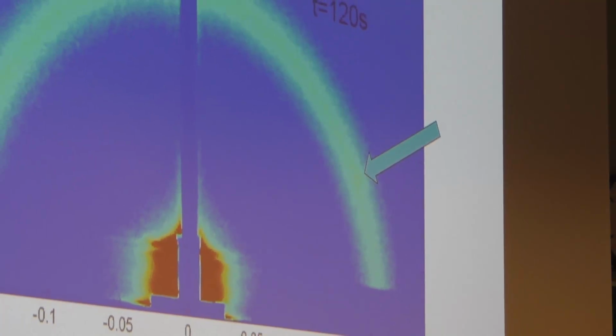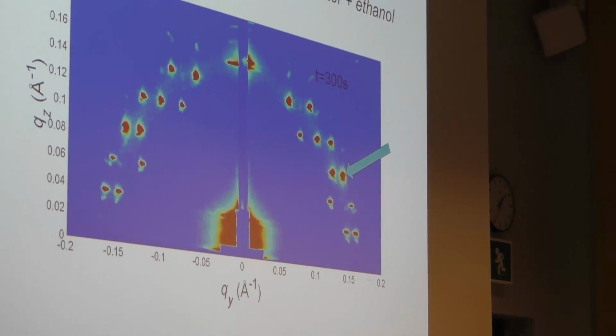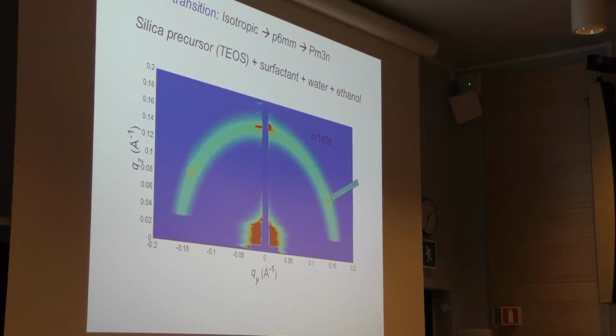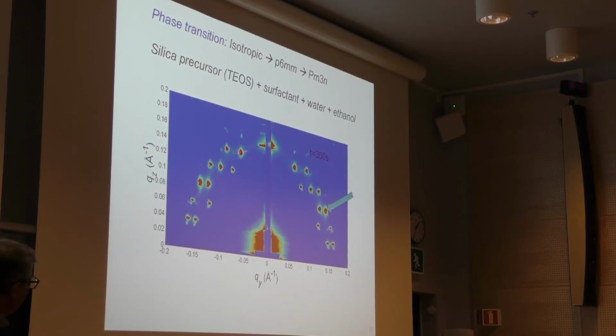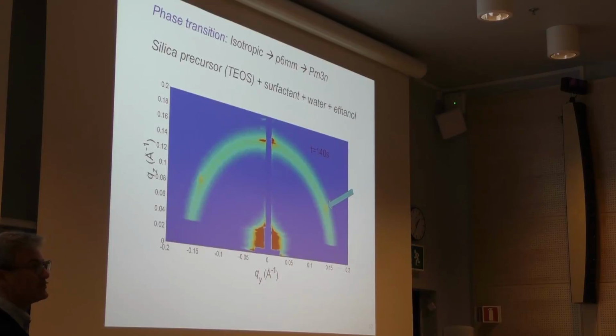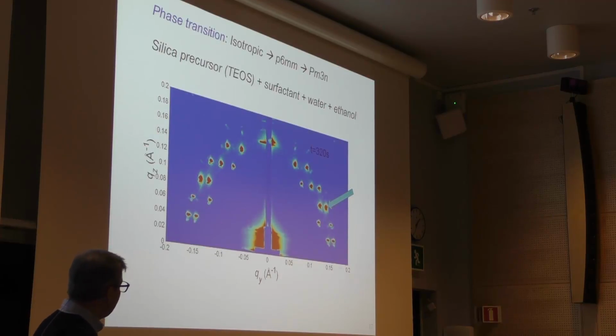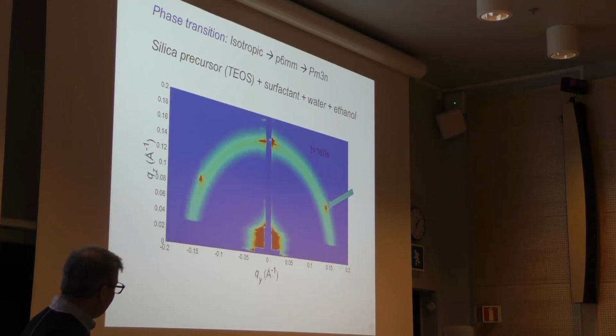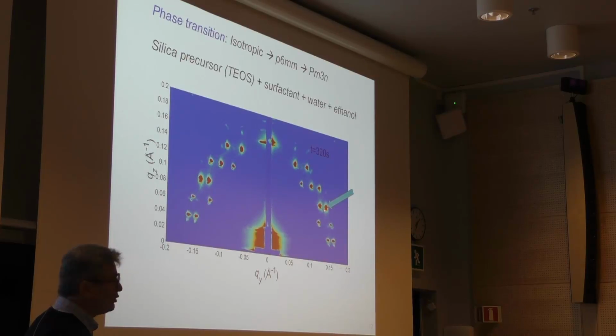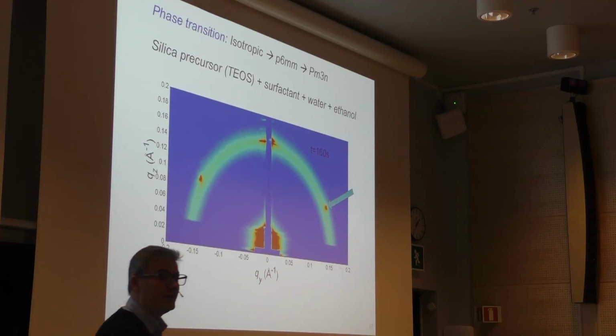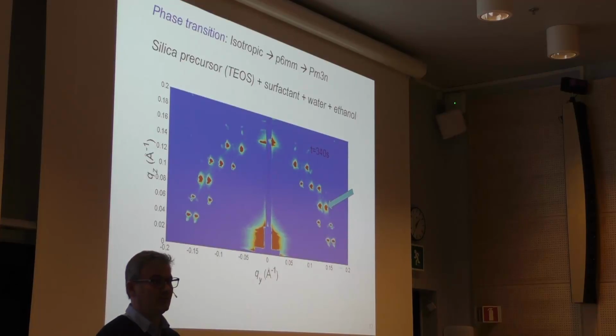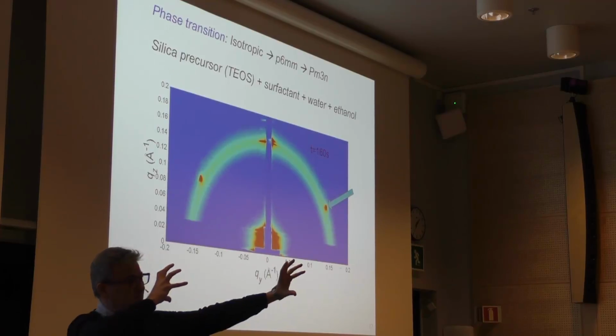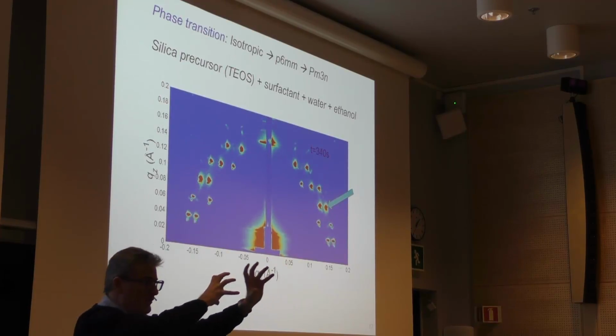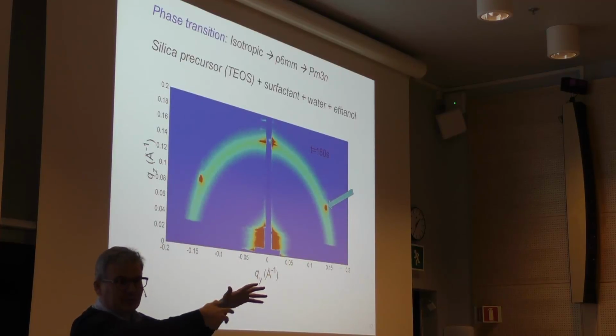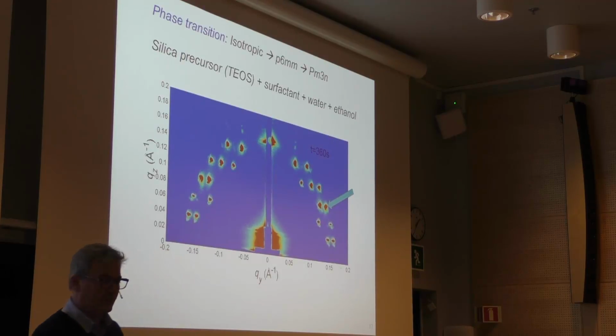The reason why I put this arrow here is to highlight that this peak coming up here, first in the hexagonal structure, stays put during the whole sequence, right? The first interpretation that we had of that was that this was a coexistence between two phases, some kind of three-dimensional structure coexisting together with this hexagonal structure. But we have looked more carefully at it, and it turns out that the correct interpretation is that this peak becomes an integral part of the arising three-dimensional structure. So what we are really talking about here is a topotactic phase transition, meaning that the cylindrical micelles that we have initially form some kind of template for the three-dimensional pore structure that comes up later.